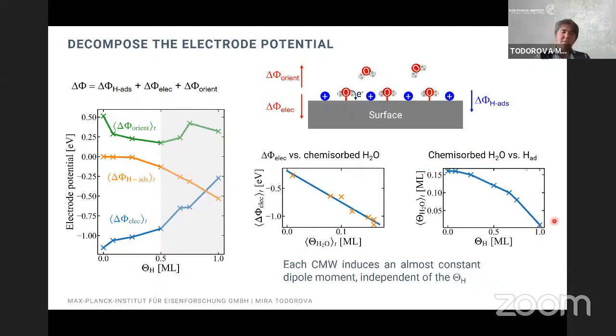So if we turn around again to this kind of plot where we plot the electrode potential contribution as a function of coverage, there seems to be kind of a transition. So up to approximately half a monolayer coverage, the two water-related contributions almost cancel each other. So they have opposite contributions and they cancel each other. The only thing that they lead to is a kind of shift of this curve, which we also find from the vacuum. At higher coverages of hydrogen,